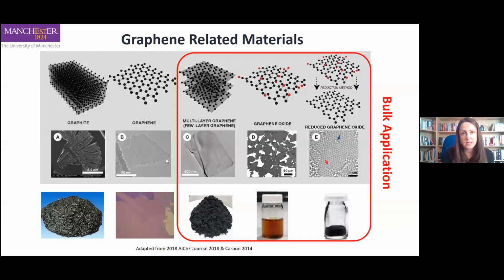The section on the right is labeled as bulk applications. So these are far more industrial, scalable routes to making graphene, and we call that the top-down approach. So mechanical or chemical exfoliation essentially separates the layers of graphite out into graphene, and then we end up with graphene of a few layers. So that can be 1 to 100 layers thick. But these graphene nanoplatelets, as we call them, still display a lot of the functionality that you get with single layer graphene, but they can be produced at scale, and they can be produced as a powder, so you can then use it as an additive like you would any other kind of additive powder.